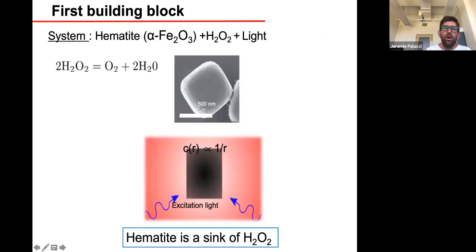So in order to make a gradient, you need a catalytic component, and the catalytic component we use is hematite. It can break down hydrogen peroxide into oxygen and water, and it's conveniently activated by light. So it's a photocatalytic material. If you take a cube of hematite, as here, which is 500 nanometers, and you put it in a uniform concentration of hydrogen peroxide, and you shine light on it, it's going to break down hydrogen peroxide. You're going to get a steady concentration profile, like 1/R. But this particle is not going anywhere, because the gradient is symmetric, and it is just a sink of H2O2.